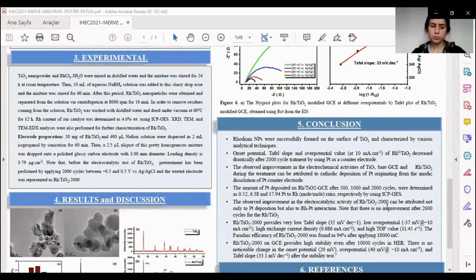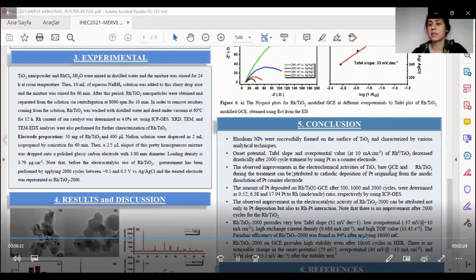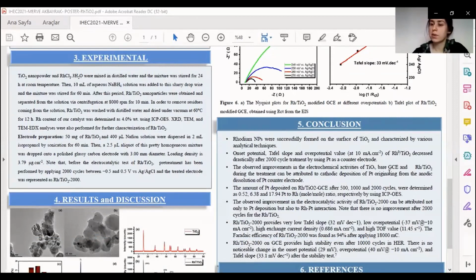As a result, rhodium nanoparticles were successfully formed on the surface of titania and characterized by various analytical techniques. Onset potential, Tafel slope, and overpotential values of rhodium titania decreased drastically after 2000 cycle treatments by using the platinum as a counter electrode. The observed improvements in the electrochemical activities of the titania, bare glassy carbon electrode, and rhodium titania during treatment can be attributed to the cathodic deposition of the platinum originating from the anodic dissolution of the platinum counter electrode. The amount of platinum deposited on rhodium titania on glassy carbon electrode after